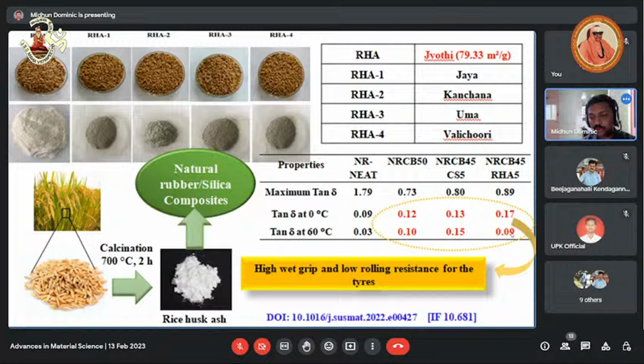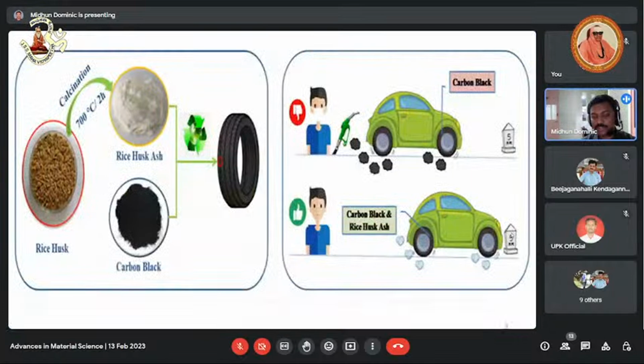By making use of commercial silica, we got good mechanical properties, good abrasion resistance index, and rolling resistance too. So we failed in improving the mechanical properties by the synchronized use of carbon black and rice husk ash, but we were able to decrease tan delta at 60 degrees Celsius. So this is the concept of green tires. The graphical abstract of the work is illustrated here.